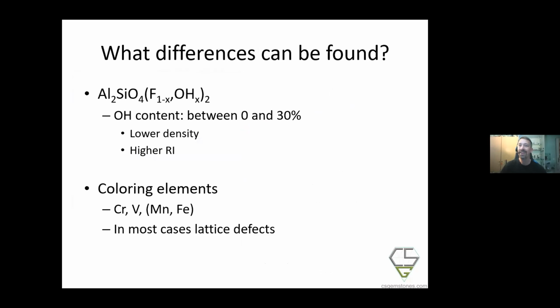I told you already, it is the difference between fluorine and hydroxyl. We can have completely 100% fluorine on the positions, and we can have an exchange of up to 30% hydroxyl in this fluorine. So we have more or less not 2 complete end members, but one end member, that's the fluorine topaz, and we can have an exchange of this fluorine up to 30% for hydroxyl. And what is the outcome of this exchange?